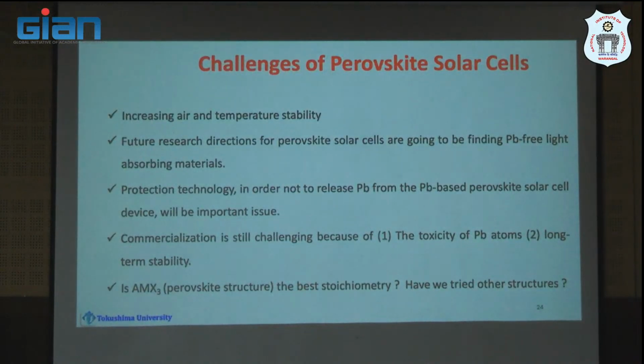It cannot show good stability at higher temperatures like 80 degrees, 100 degrees. When light energy is coming, outside, even though it is 40 or 45 degrees, if you check the temperature at the solar cell, it is more than 100.